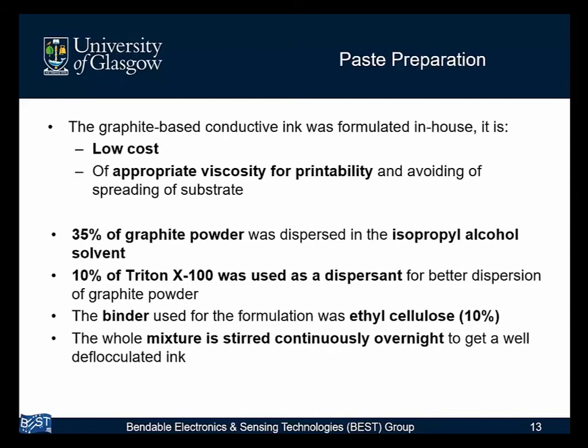Now, in terms of the paste, which might be a bit more interesting because we can tweak it quite a lot more, although we can tweak the fillers in the thermoplastics as well. But in terms of the ink, if you see some examples of 3D printed circuits, a lot of them are planar, first of all, but not only that, a lot of them use silver ink. Silver ink is quite expensive, but not only that, commercial inks don't allow us to alter the properties in terms of viscosity and the specific properties which we need for repeatable printability. So we've used an in-house formulated graphite-based conductive ink.